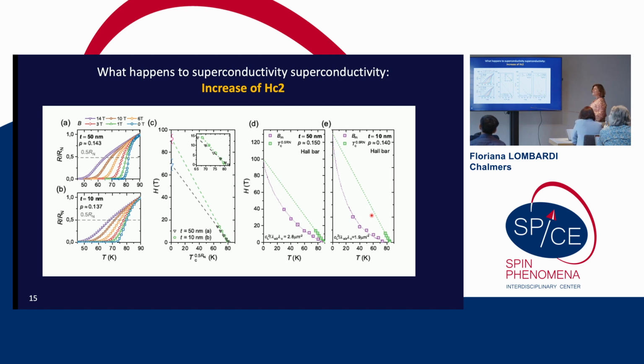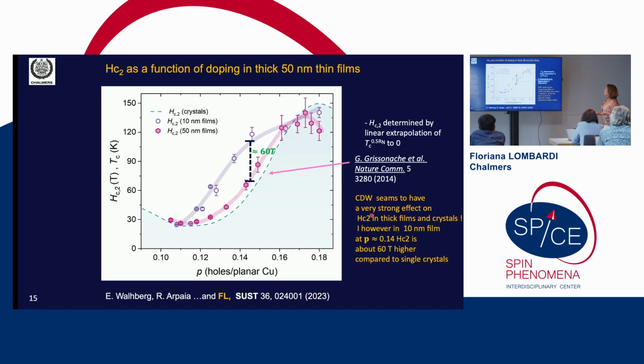But then we made the experiment considering vortex melting transitions, and we also see that the concavity for 50 nanometers and for 10 nanometers, at much higher fields, because we went to 50 Tesla, are completely different. Nevertheless, the field that you can extrapolate at zero temperature is the same for these simple measurements and the vortex melting measurements, and it is much higher in 10 nanometers compared to 50 nanometers.